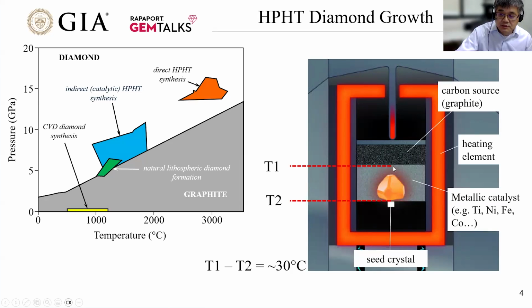It's very important to keep a temperature gradient between the point here, temperature T1, and here, the diamond seed. So the temperature at the center, T1, is about 30 degrees higher than the seed. That is a very important technology to make sure carbon dissolves more into the liquid at a high temperature. When it circulates to the lower temperature area, carbon becomes oversaturated in this liquid metal, and the oversaturated carbon deposits easily on this diamond seed as a single crystal. This is basically the principle invented by GE in the 1950s, in 1954. Now, obviously, the technology has been greatly improved. Instead of growing one large crystal, multiple crystals can be produced simultaneously at high pressure and high temperature.